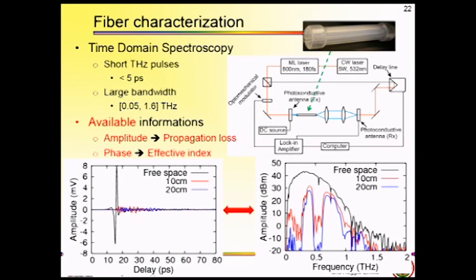The characterization has been performed through a terahertz time domain spectroscopy system, which is represented schematically here. The interesting part of this setup is that you have pulses that are produced by our photoconductive antenna here, and they pass through the fiber, and are then recollected and refocused at the photoconductive antenna. Since we are dealing with pulses, we are working intrinsically with a broadband feature, so we can determine both amplitude and phase information, which allows us to calculate both dispersion, which is the effective index for the fundamental core mode, and the propagation loss.